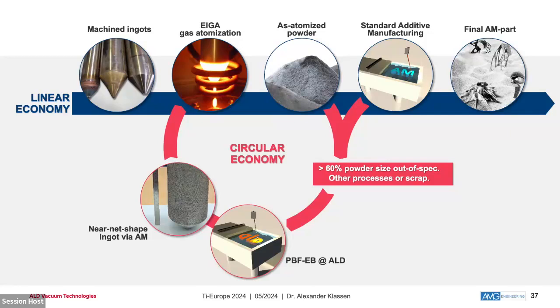And we found a means for recycling by just putting it again back into the additive manufacturing system, which is what we can do. Why? Because of the missing restriction for the powder particle size distribution. And then we produce ingots again and put it back to the EIGA atomizer and close the material circle.